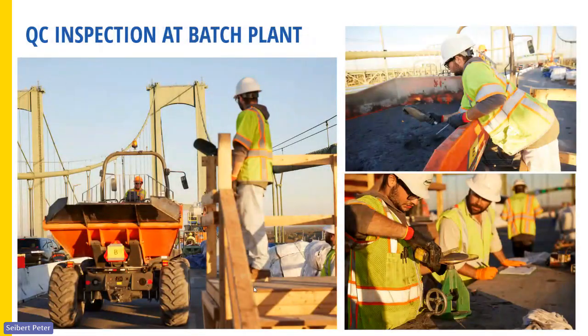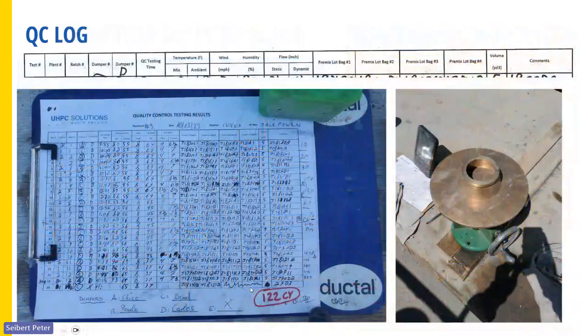Then there's the QC inspection. For every batch that was done, the material was dumped into these dumpers. They drove up to the QC station where young Jack took a scoop and did the flow test. We also recorded for each batch the static and dynamic flows, temperatures of the mix, the timing, and what material was used from which bag. So we had a detailed understanding where the material was placed on the bridge.